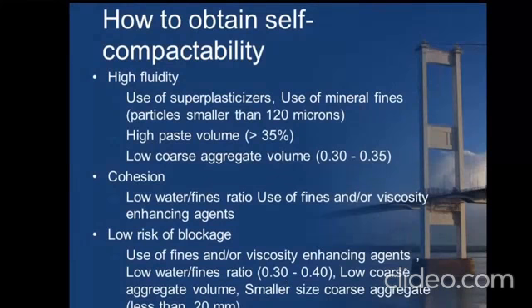So as I told you, the coarse aggregate should be less than 20 mm preferably. But nowadays I could see many papers with self-compacting concrete where they are using the same gradation, but they just make a proportioning. They say 60% of aggregates down 12 mm size and then 40% of 20 mm aggregate size. But generally, it is always advisable to use a lower fraction of aggregate in order to get a good flowable concrete in terms of self-compacting concrete.